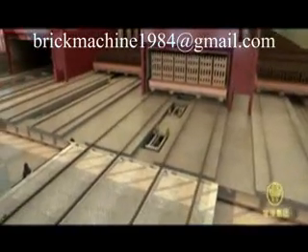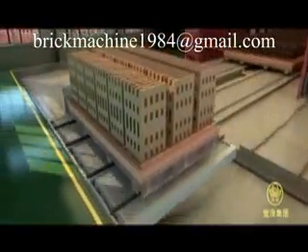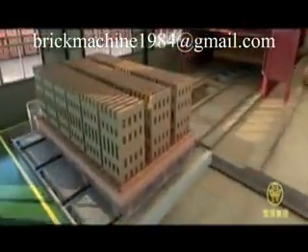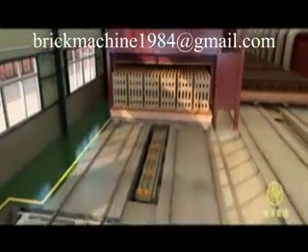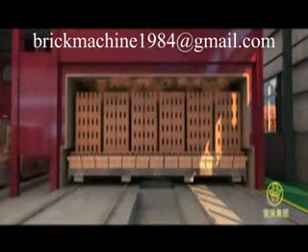After thorough drying, the kiln cars are dragged to the entrance of an assembled-type tunnel kiln by a tractor. A hydraulic kiln car pusher then pushes the kiln cars into the kiln. After 40 hours of preheating, firing, and cool-down, the finished bricks finally come out.